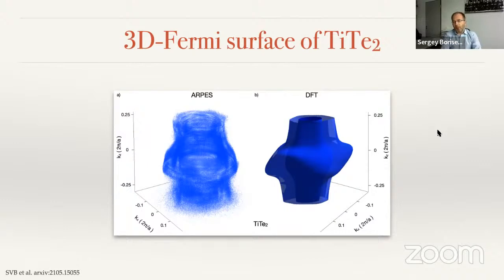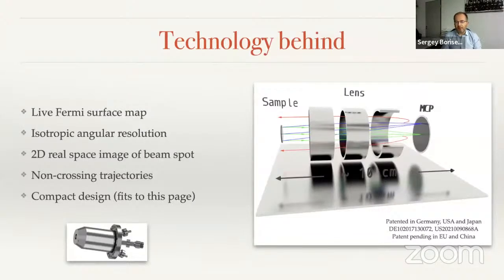This way of collecting data became possible because we patented a novel technology, which is surprisingly very simple. What we use is the usual conventional electron lens, which does a Fourier transform, meaning that all electrons which left the sample at a particular angle will be focused at a single point at the detector, and those which left at a different angle will be focused at a different point. This has been used already in conventional analyzers.